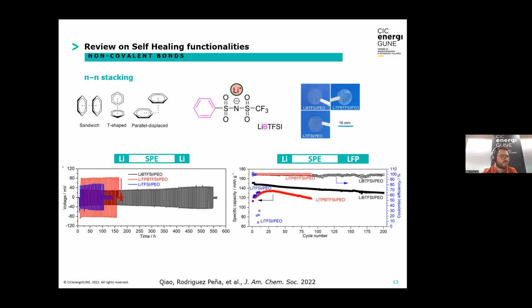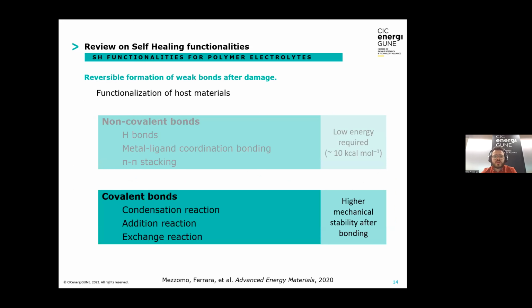iron phosphate positive electrode. In terms of covalent bonds, self-healing via these covalent bonds may offer improved mechanical strength to the bulk material. However, the reversibility of this bond is shorter, and an external stimuli, such as application of temperature, is generally required to induce this recovery. Therefore, the energy required is higher than for non-covalent bonds.